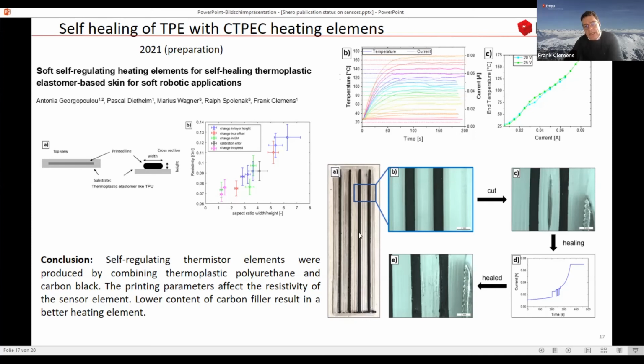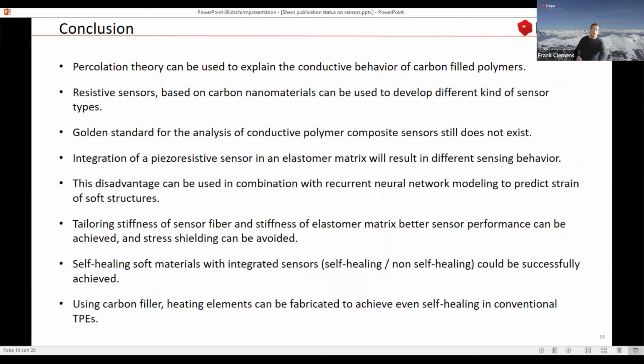Then we heated the material up, which you can achieve by applying different voltages or by making a cutoff of the current. By this, you can adjust the certain temperature which you need. We placed the temperature close to the melting temperature of the TPU matrix material which we had. We made a cut inside, which is what you can see here. By heating up the elements, you can see that we could close this cut and self-heal the TPE material.